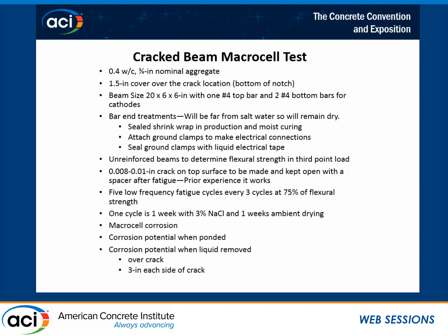Once again, the crack sizes were trying to be between 0.008 and 0.01 inches. These are below what is normally allowed in codes for this structural capability, but for cracking, those are large size cracks, as you'll see. We cycled them 1 week with 3% sodium chloride and 1 week ambient drying. We measured the corrosion current, the corrosion macrocell currents, and the potentials, and we looked at that over the crack and away from the crack.